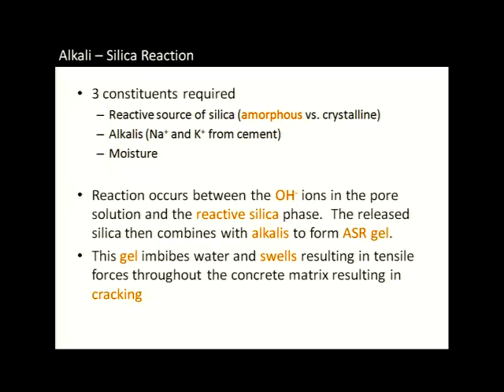So for concrete in an interior like this, like these concrete columns, the floor that's below us, that's not going to be susceptible to ASR because there just isn't enough moisture available to drive the reaction. We typically need an internal relative humidity above about 80% to drive ASR. So the main places that we see ASR are in transportation infrastructure and concrete that's exposed to the environment. So dams, pavements, bridge columns, bridge decks, those are all typical places where we see ASR.